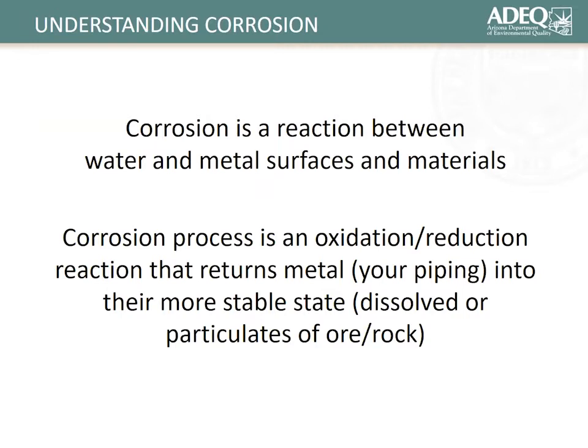Mostly, I think in our state, when we really try to break down some of the results that we get in, what we see most of the time is lead particulate, which tells us that a scale broke off, versus dissolved. When you start seeing dissolved, that's an indicator that the metal is directly in contact with the water, and that's not what you want to see.